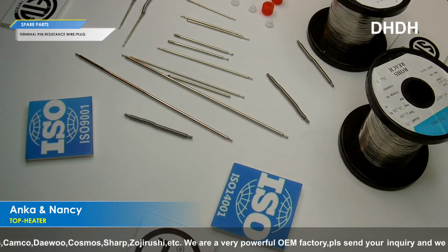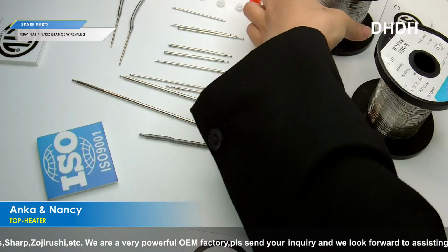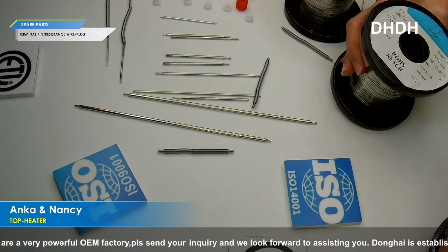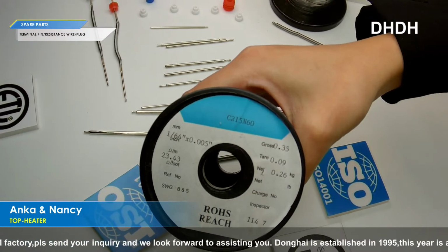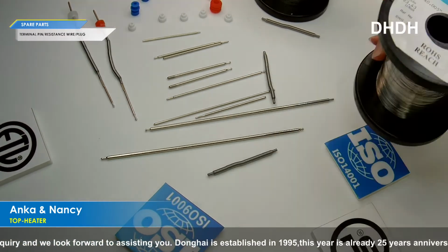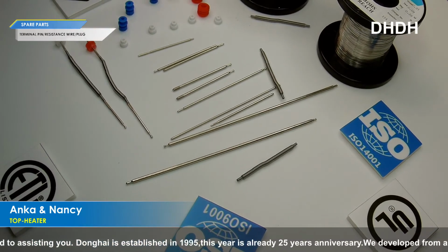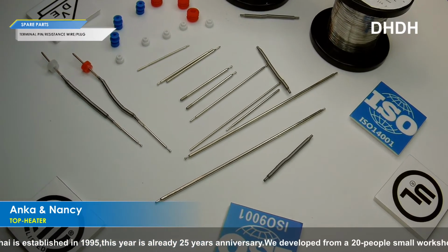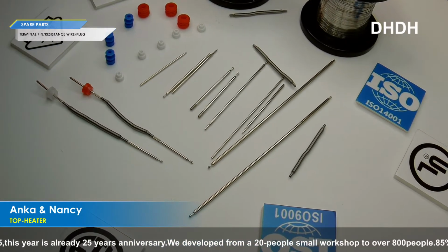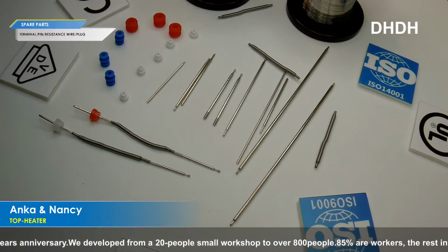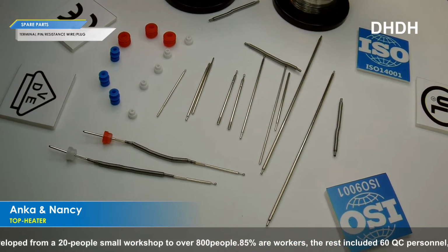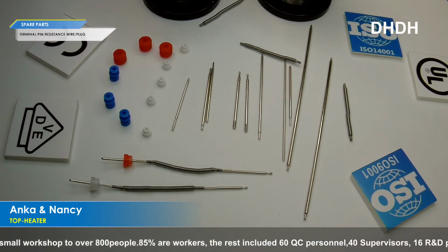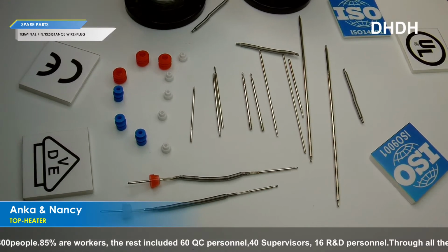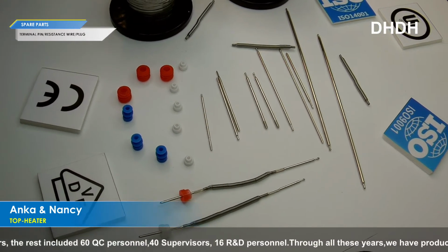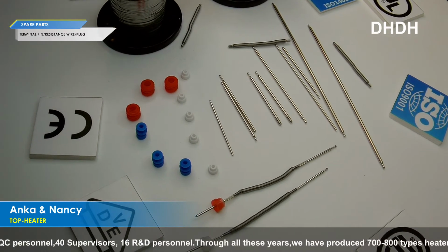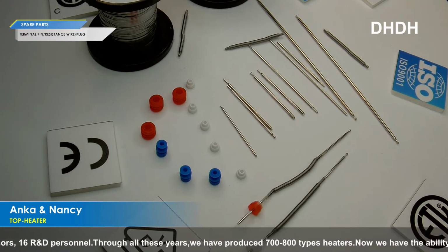such as nickel 80, chromium 20. This one, for example, is chromium 15 and nickel 60. For such material, the high temperature strength is higher than that of iron, chromium, aluminum. It is not easy to deform under high temperature use, and it has high emissivity, strong corrosion resistance, and long service life, and so on. Because it is made of the rarer nickel metal, this material is actually several times more expensive than the iron, chromium, aluminum material, and its use temperature is lower than the iron, chromium, aluminum resistant wire.